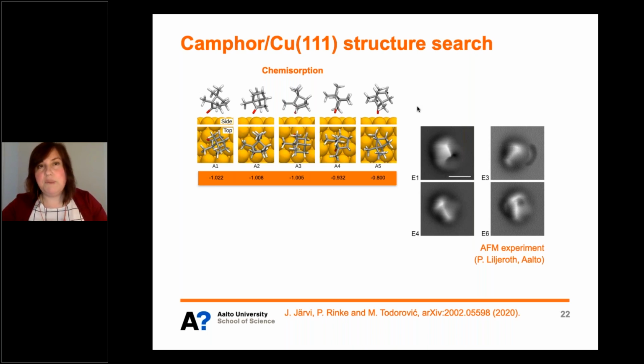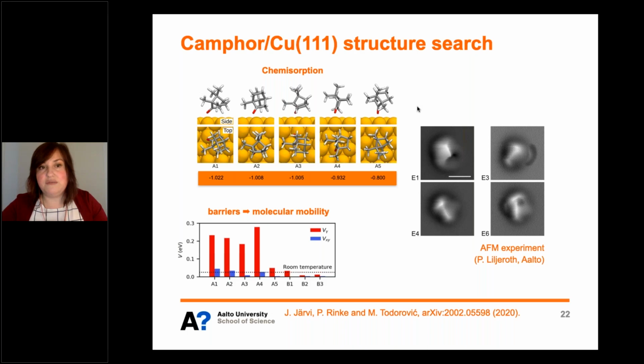So we went back to our potential energy landscape and we data mined it for all kinds of barriers. On this graph, you see the blue barriers correspond to lateral mobility for diffusion along the surface, and the red barriers correspond to kind of in-place rotation. And it's really these four structures that look like the best candidates for really stable and static structures on the surface. And now we're in the process of identifying it. And if you want to know more about this work, you can read it in this freshly archived paper.